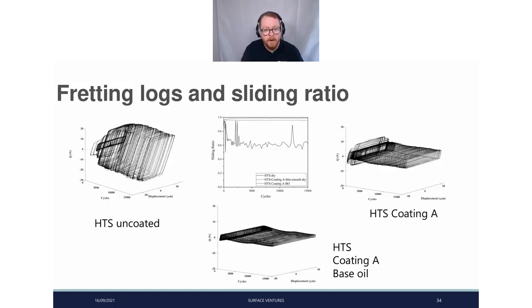And then we can look at our fretting logs and our sliding ratio. So also these with different types of lubricant. What we can see uncoated is that we have our instability right at the beginning. This then extends into our set gross slip as the machine's feedback loop kicks in and is able to keep this within the measurement parameters. We see that again with coating A, this instability. However, the friction force is far smaller. Our energy expended is far smaller, and then far smaller once again with base oil.